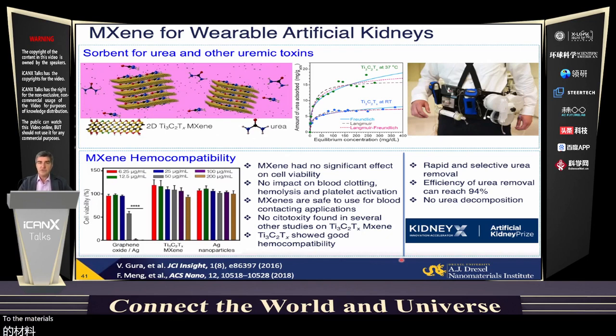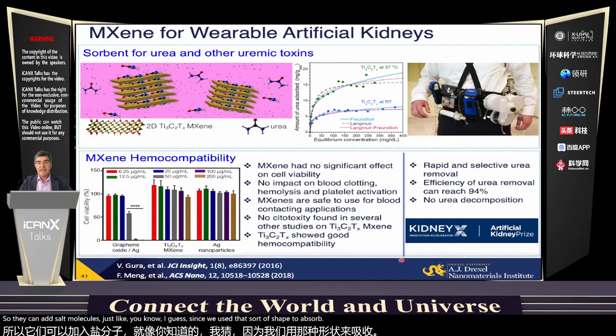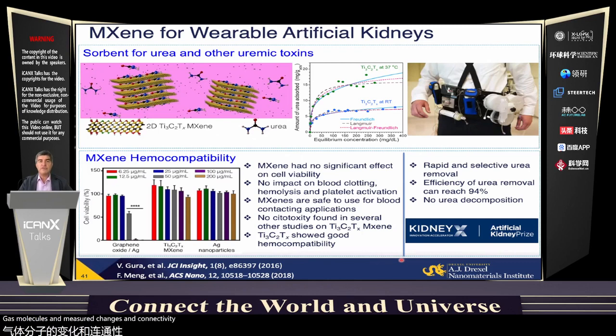2D materials naturally have high surface area, so they can adsorb molecules. Just like in a gas sensor, we use adsorption to adsorb gas molecules and measure changes in conductivity for sensing purposes. In batteries and supercapacitors, ions are intercalated between the layers. But it also appears that MXenes, particularly titanium carbide Ti3C2, and this is so far the most studied MXene, can very effectively adsorb urea molecules. And actually, what has been limiting development of wearable kidneys? There is no good sorbent for urea. Activated porous carbons, which are excellent sorbents for the majority of biomolecules, are very poor sorbents for urea.